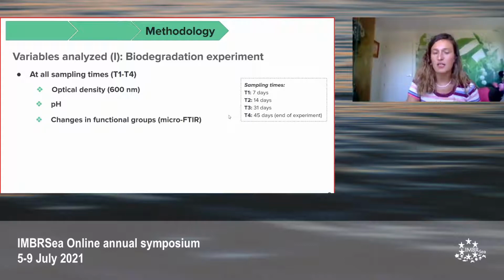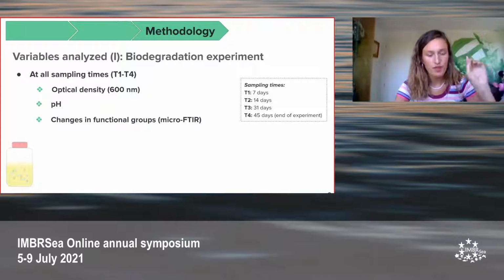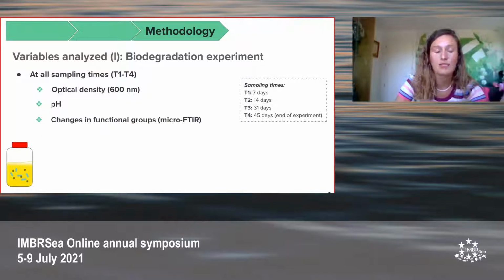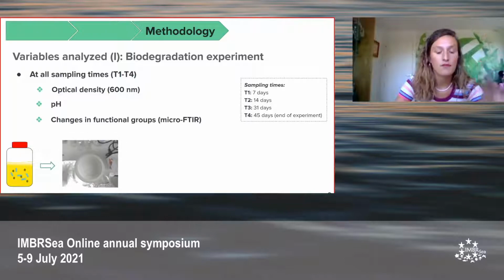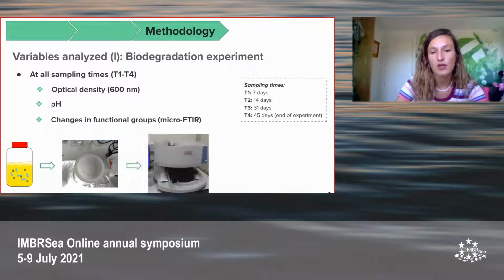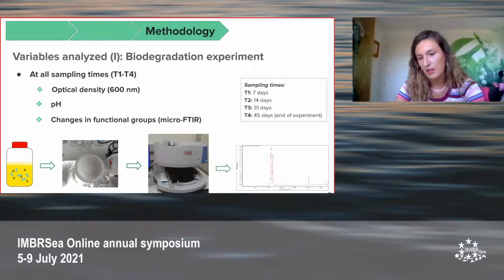FTIR is a widely used tool for polymer degradation, as it allows for the straight identification of absorption bands at given positions that can be modified as polymers degrade. This way, each glass flask at each sampling time and treatment was filtered to obtain the plastic particles, and 3 of these plastic particles were analyzed through FTIR to obtain the respective spectrum and compare it among